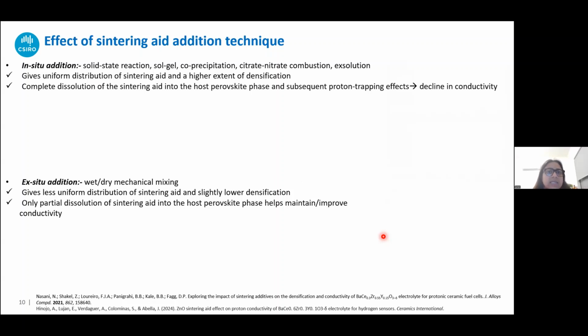Now, the next thing is the effect of the sintering aid addition technique. As I already mentioned, there are two pathways. One is the in situ addition. Here the sintering aid is added at the very initial step, during the solid state reaction, sol gel method, co-precipitation or exsolution. This gives a more uniform distribution because we are adding it during the synthesis, at the first step itself, and that leads to higher densification.